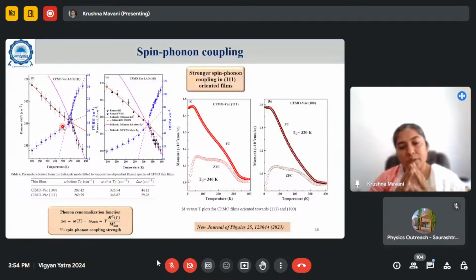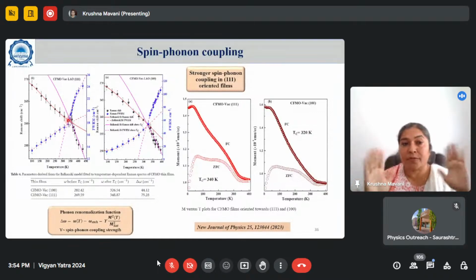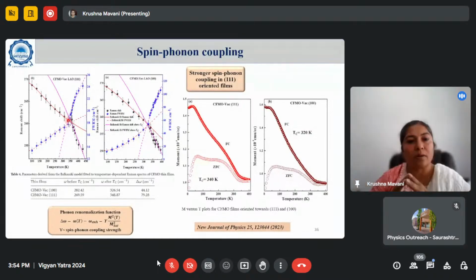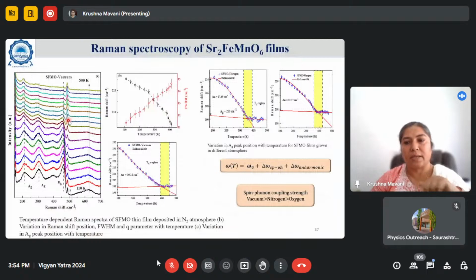So this is the first such experimental observation found in double perovskite thin films, which was published in New Journal of Physics recently. Earlier, no such spin phonon coupling has been reported in the bulk of these materials. Only thin films are showing this kind of coupling, and we could experimentally observe it by various techniques.